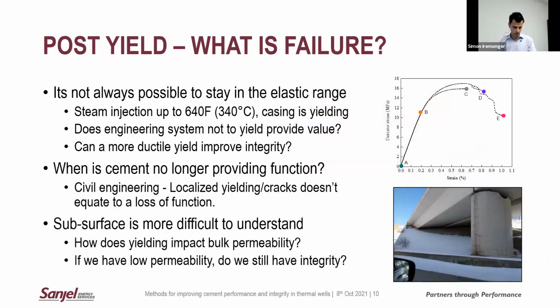So, continuing to build on this and really try to understand what is this complex failure process, what does cement look like post-yield? This is especially a problem for us dealing with cyclic steam injection, where we have clients potentially injecting steam all the way up to 340 degrees Celsius, 640 F. At that point, your casing is yielding. That's an accepted thing in the industry here.